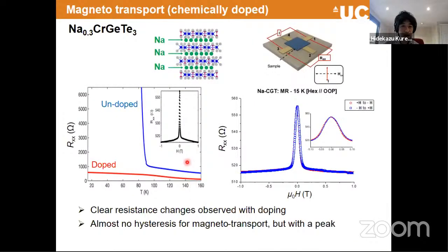And just to give you a quick result. This is the resistance as a function of temperature again, but in this case, we put sodium inside this CGT van der Waals layer gap. Similar to the electric field one, this is an undoped case, but when doped, we reduced the resistance fairly well. We also show a different temperature dependence of the resistivity, not quite like a metallic regime, but we are nearly there. And when we measure magnetic transport, now this is the Rxx component as a function of out-of-plane magnetic field.